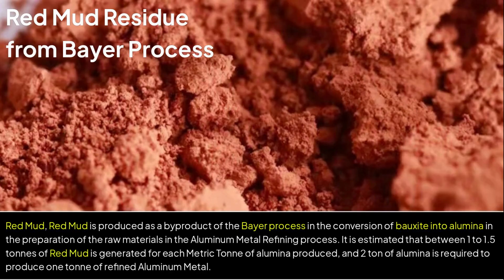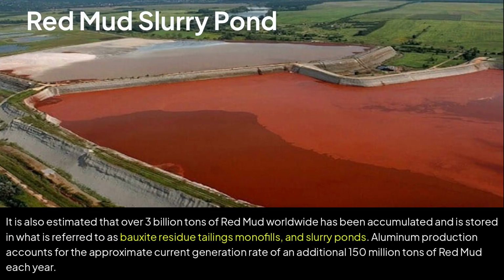Red mud. Red mud is produced as a byproduct of the Bayer process in the conversion of bauxite into alumina in the preparation of the raw materials in the aluminum metal refining process. It is estimated that between 1 to 1.5 tons of red mud is generated for each metric ton of alumina produced, and 2 tons of alumina is required to produce 1 ton of refined aluminum metal. It is also estimated that over 3 billion tons of red mud worldwide has been accumulated and is stored in what is referred to as bauxite residue tailings monofills and slurry ponds. Aluminum production accounts for the approximate current generation rate of an additional 150 million tons of red mud each year.